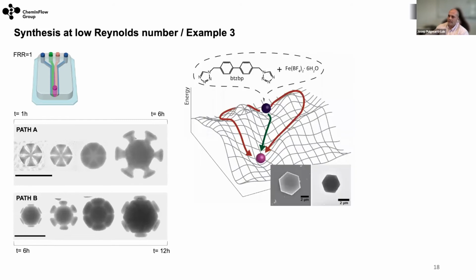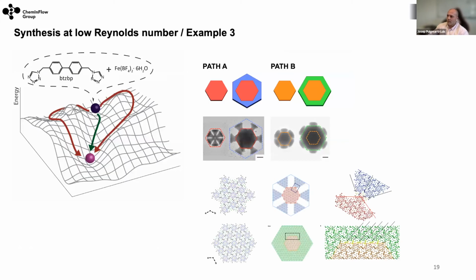So what this clearly tells us is that what we are observing are 2 different pathways of crystallization for the same product. At the end, as I said, we always obtain the most thermodynamically stable form. This was done by Guillermo in Valencia. We started to think about what the effect was, I mean, why the vertex growth would be first. He was looking at the crystal structure, and what we realized is that if the growth goes this way, we will have more ionic interactions, whereas from the faces, this will be mainly triggered by van der Waals interactions. So this is why we thought it reasonable that the first growth will be from the vertices and later on from the faces.